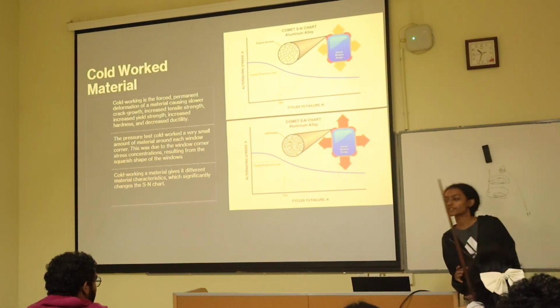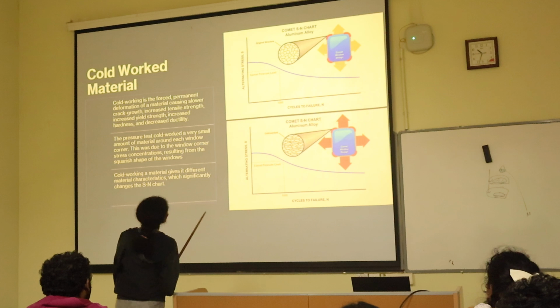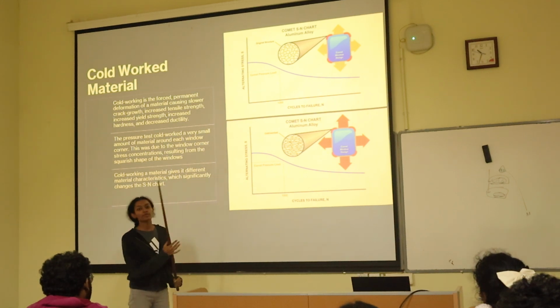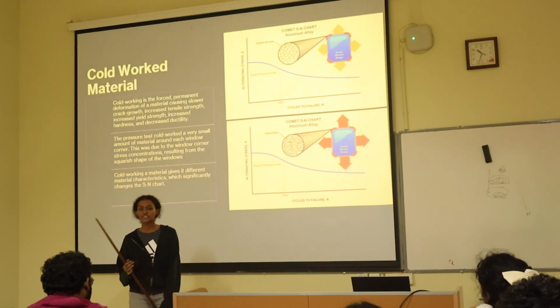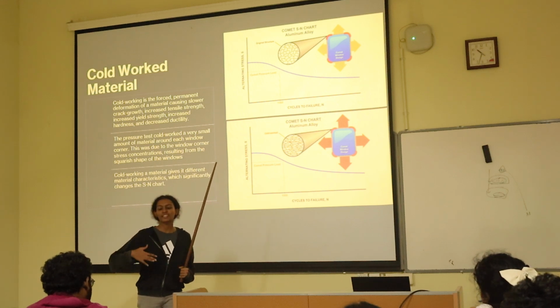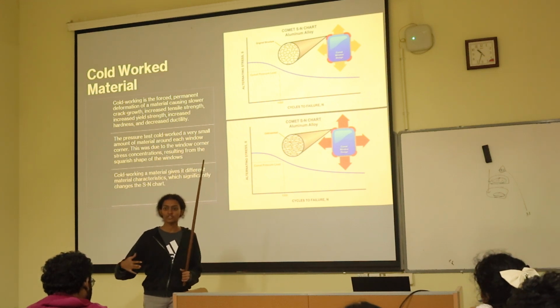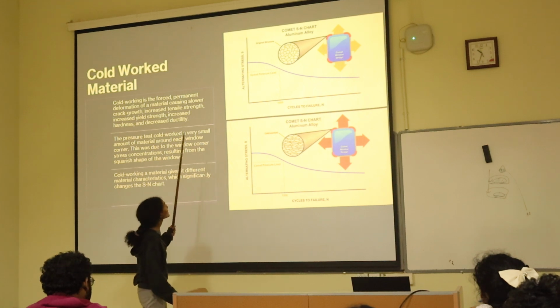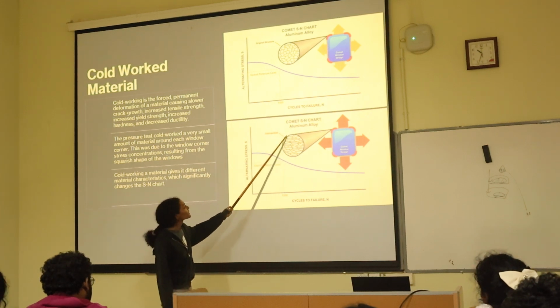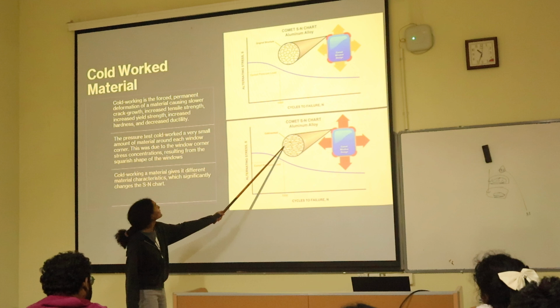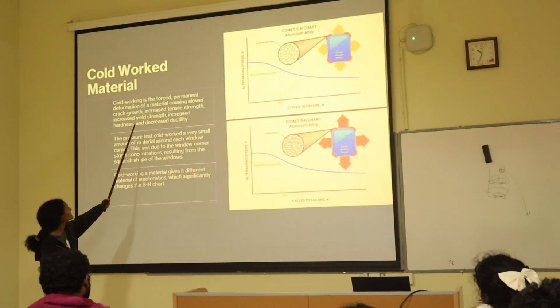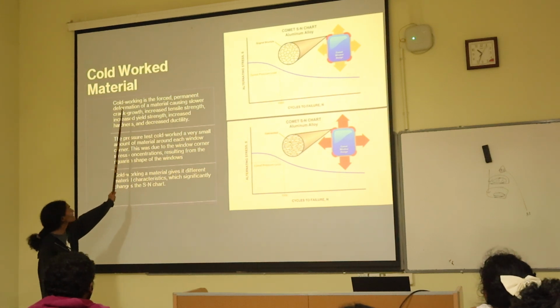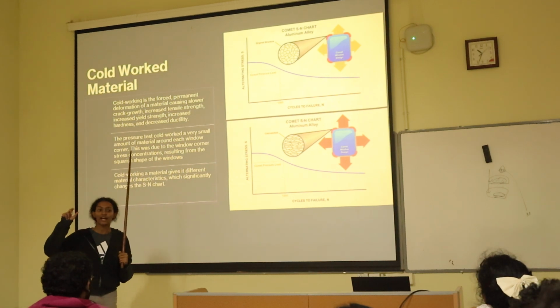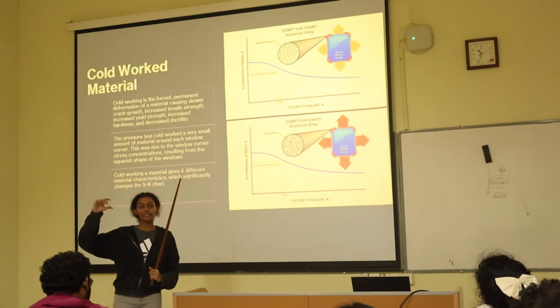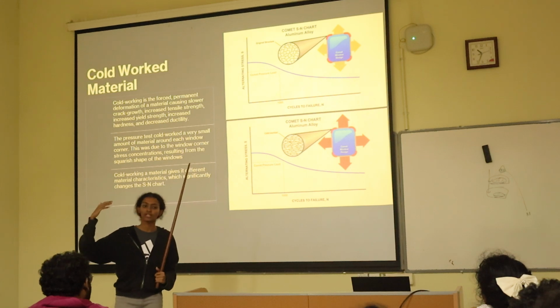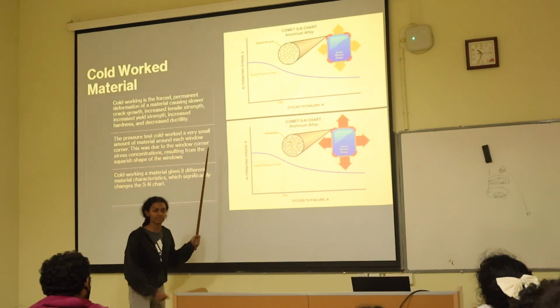Just to give some view of what Anish said. Initially, a pressure test was conducted, at an excess pressure, just to be safe. When this was conducted at 2P, the material got cold worked, and in cold working, the tensile strength and yield strength increase at the points of high stress concentration. This is because at these points there are higher dislocations, so there will be pinning of dislocations, right?